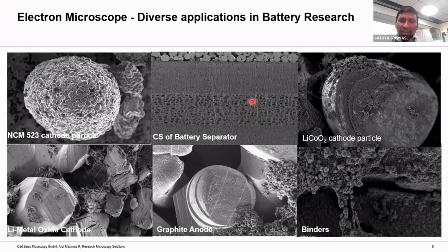So if you want a clear understanding of those pores and you apply a higher kV to such samples, the pores degrade at the surface, and you don't get the actual information. But with the field emission scanning electron microscope technique, with a low kV, you can resolve such beam sensitive surface features.